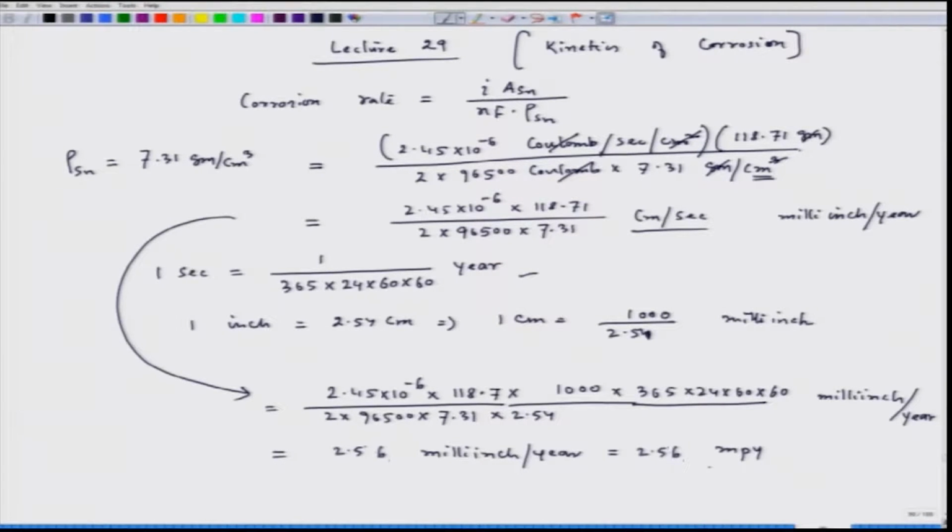So we could see that we can express the corrosion rate by using the corrosion current density, and then we can convert it into either MDD, that means weight loss per area per unit time, and also into MPY, which is milli-inch per year. So, we can convert it into uniform as well as localized depending on the surface nature of that particular metal in that particular corrosive environment.